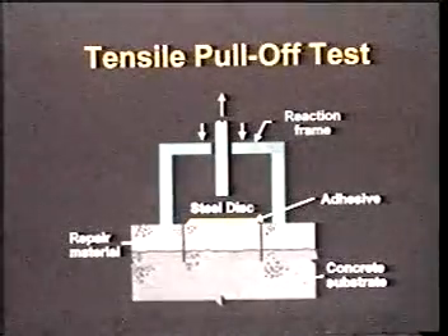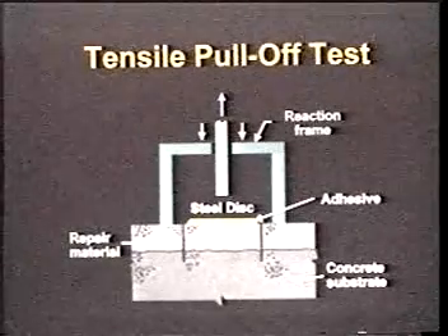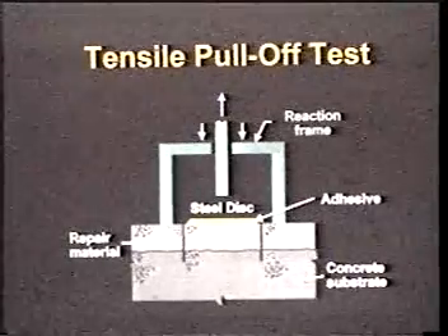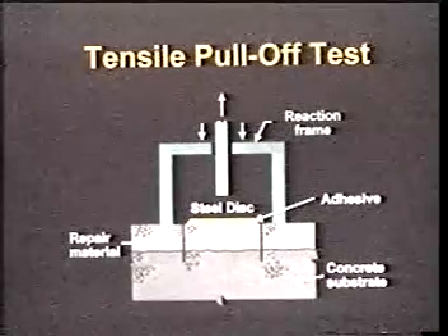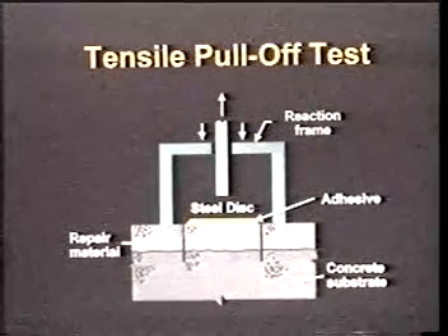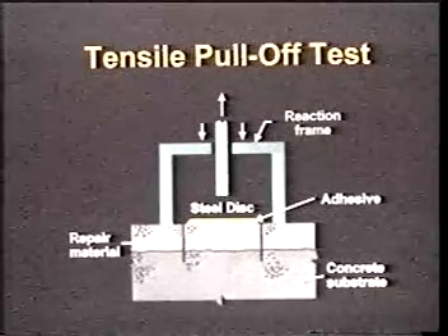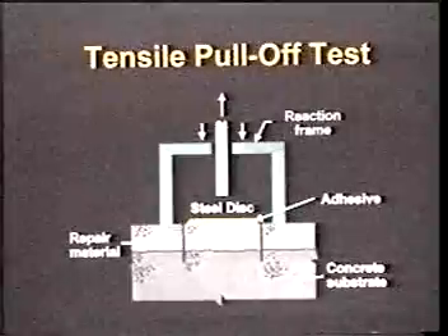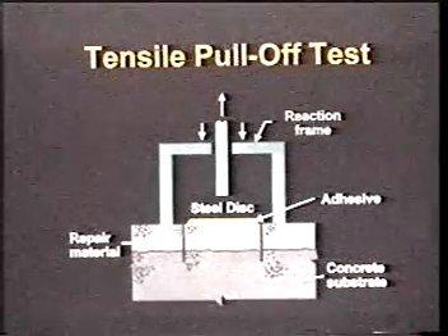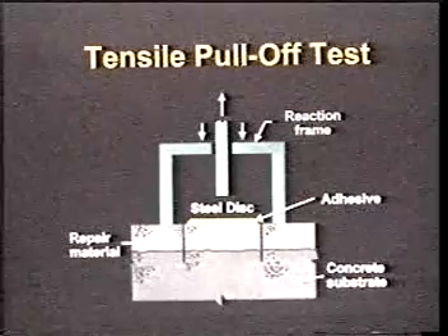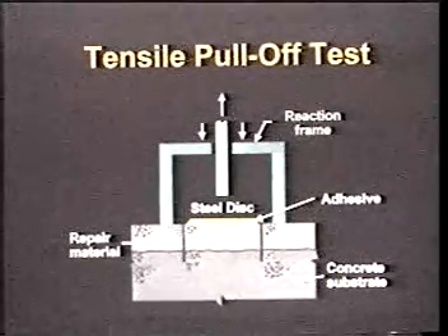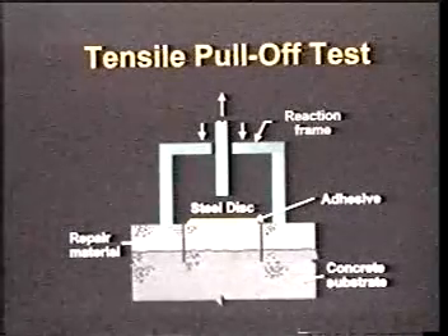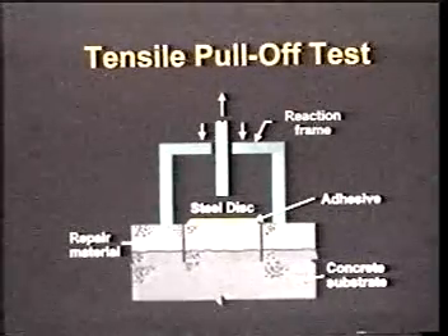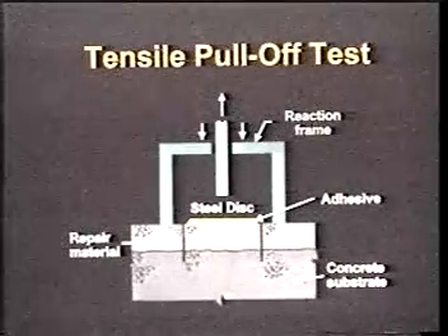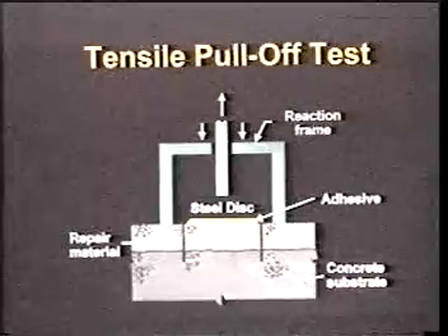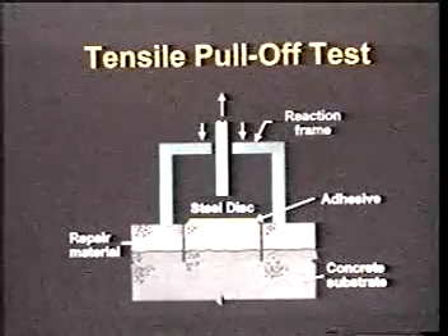So this is schematically shown, the tensile pull-off test. There are quite a few different devices in Europe and in the United States which we are using to evaluate this tensile strength. Quite straightforward, quite easy, a very good concept. You probably know very well, and understand, that the failure in predominant cases does not occur in tension in this system, it occurs in shear.